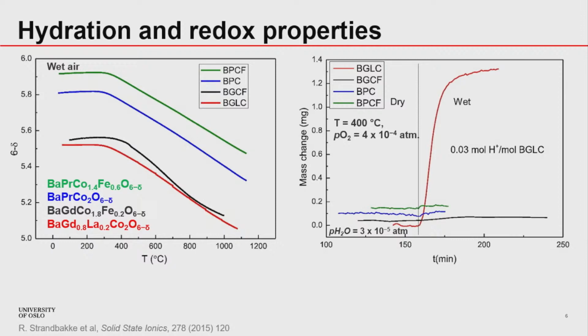But the moment we switch to a wet atmosphere with a pH2O of 0.02, we see the BGLC, the red color sample, showed an increase in weight. This indicates the hydration of the BGLC material. Given that the hydration is happening just because of the filling up of the oxygen vacancies, we can calculate the moles of protons per mole of BGLC. For this particular sample and this atmosphere, there is 0.03 mole of protons per mole of BGLC. So here we saw how we can correlate the oxygen non-stoichiometry with the hydration of the materials in the TG.